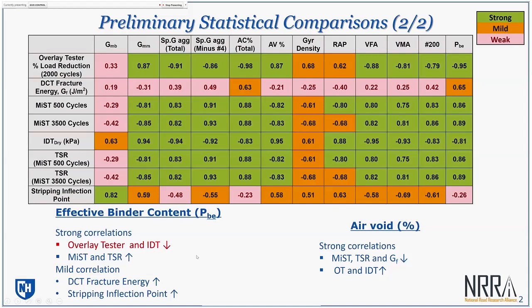So that's somewhat counterintuitive, because typically you'd expect higher binder content to have better performance. What we are also seeing is tests for durability, such as MIST and TSR, increase with binder content, not necessarily surprising. And also things like DCT fracture energy and Hamburg results on rutting were both improving with increasing effective binder content.